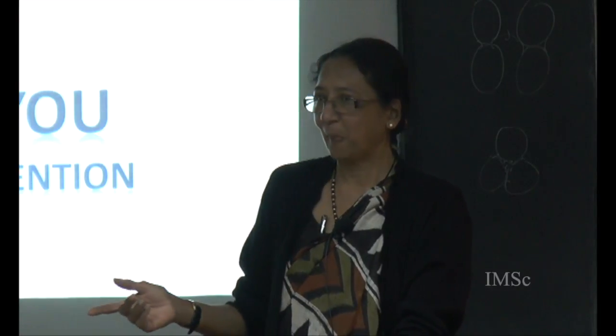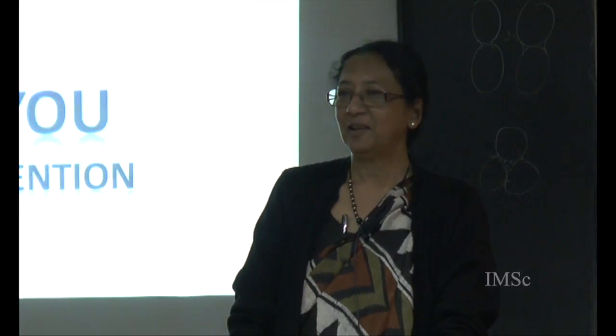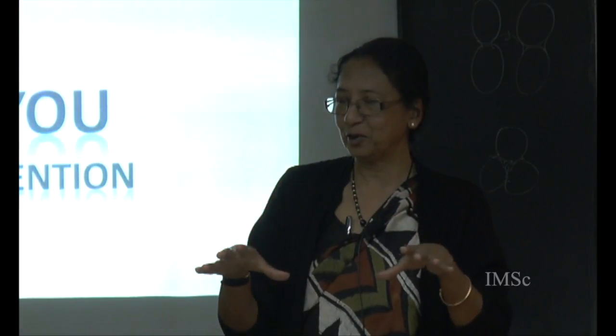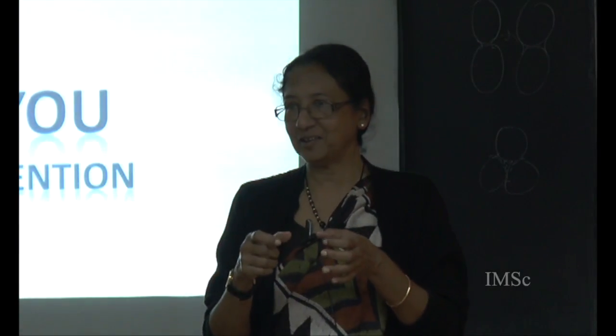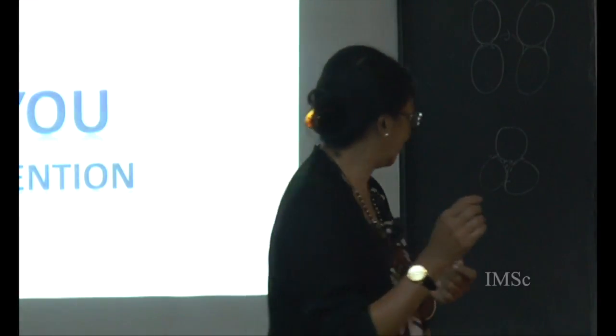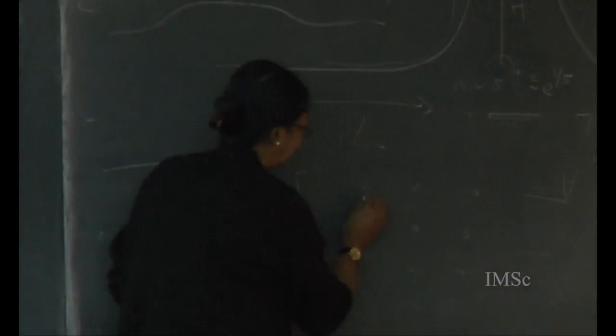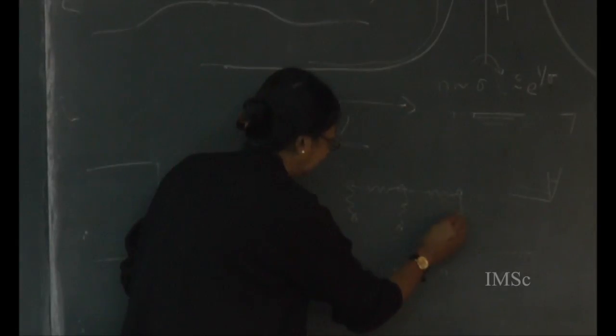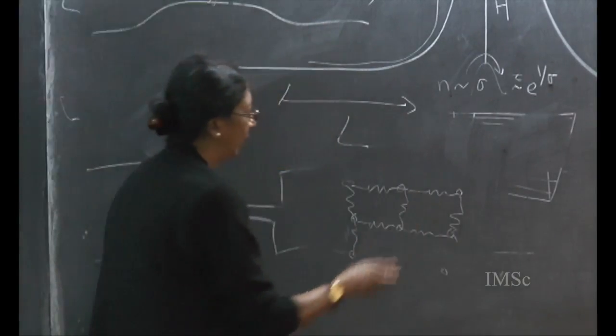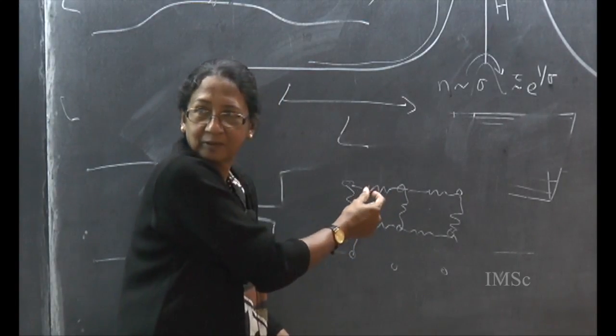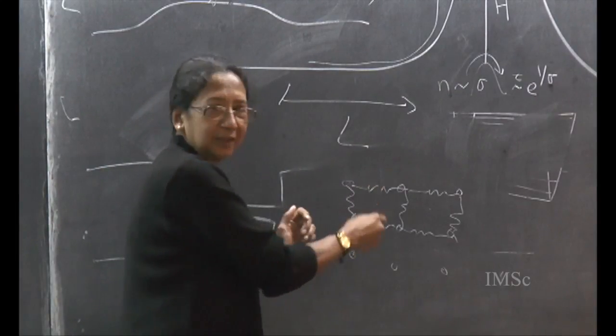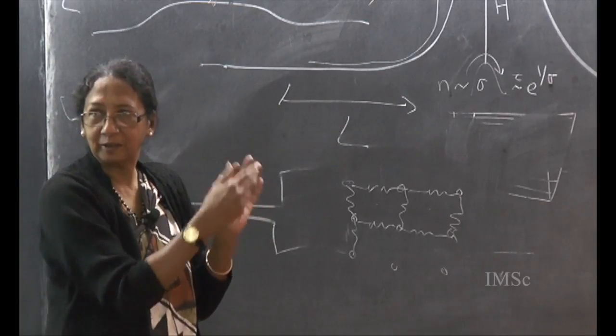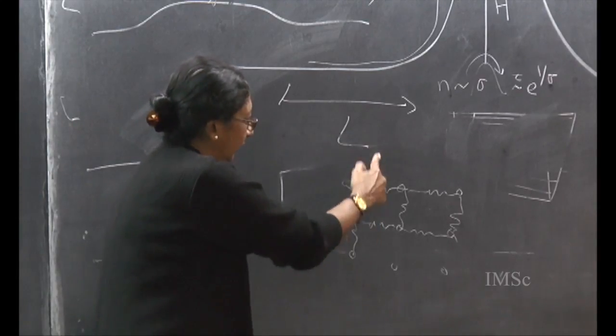Now, when we modeled this system with our spring network model, we made an assumption that the particles are moving in the direction of the field. So that is one type of motion of the particles, and in addition, there is also desiccation. We can maybe show it here. We have particles attached by springs, something like this, and the effect of desiccation is to shrink these springs. So that will produce forces, and if the strain goes above a certain limit, the spring will break, and that will be a crack. I mean, if these are broken, then we have a crack here.